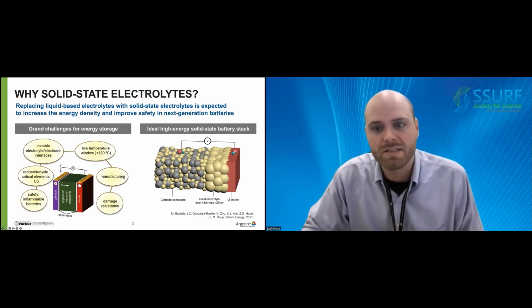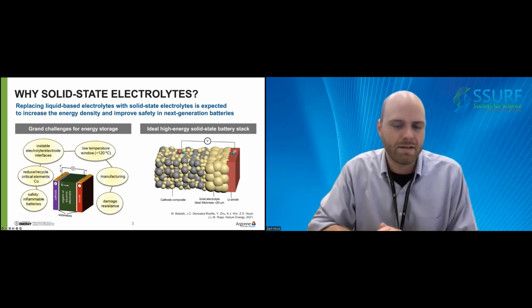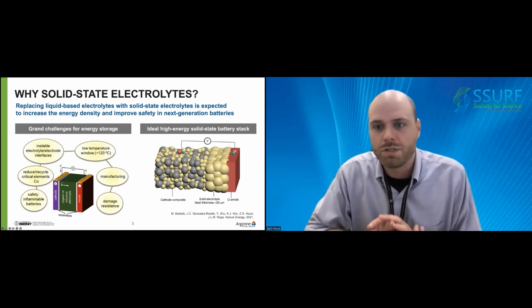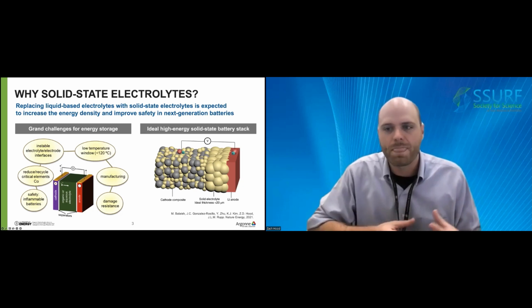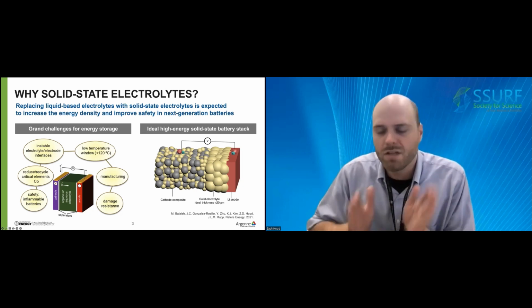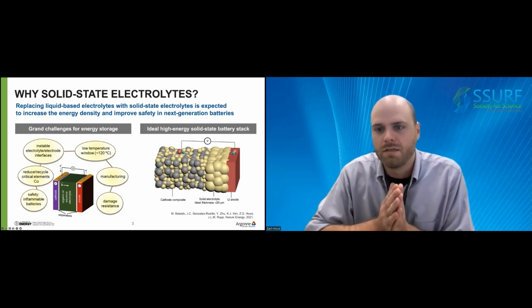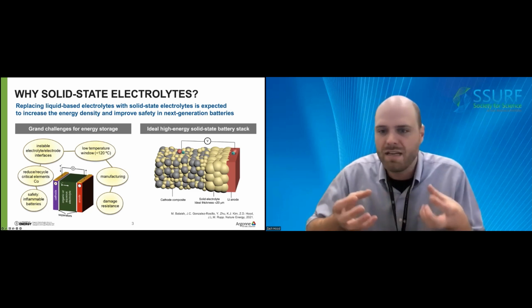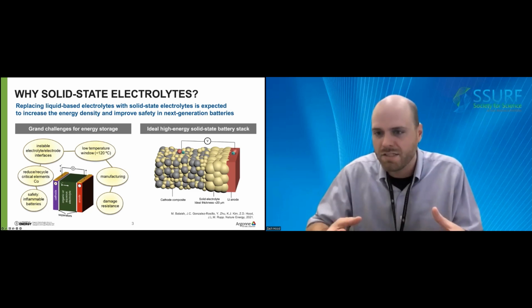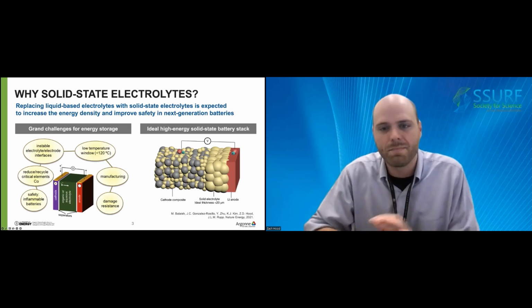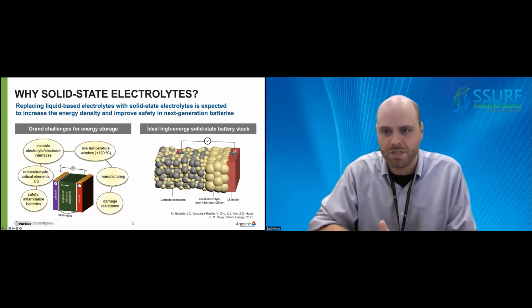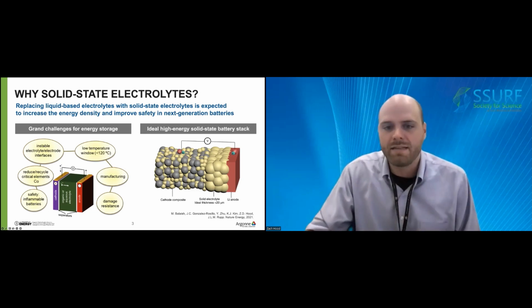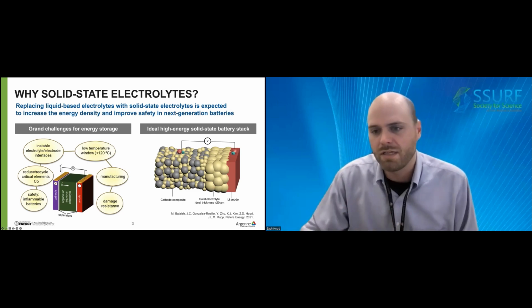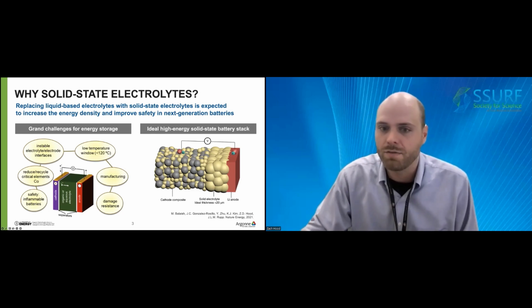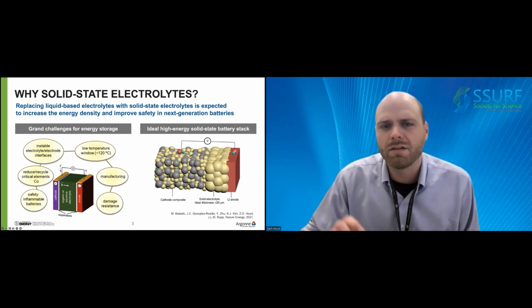On the right-hand side of the slide, I show an ideal high-energy battery stack, which is composed of a composite cathode, a lithium metal anode, and a solid-state electrolyte between the two. The solid-state electrolyte is envisioned to enable energy-dense anodes and cathodes that will allow for batteries with higher specific energies. But note that this idealized battery structure requires a solid-state electrolyte with a thickness of around 20 microns or less. So let's take a quicker look into